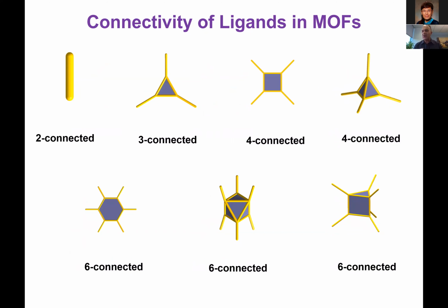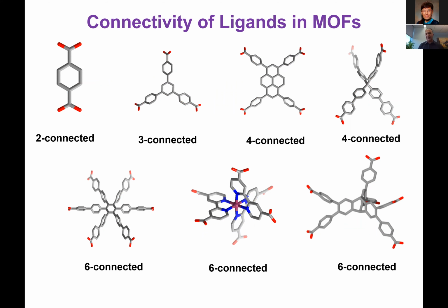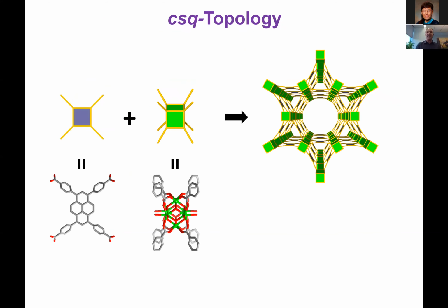With the organic ligands, we could play the same game. From 2 connected, that means you have, let's say, 2 carboxylic acids, 2 pyridines, 3 connected, 4 connected. The 4 connected can be a simple square or a tetrahedron, and the 6 connected can be an octahedron or benzene-like. So now we could start thinking about those geometric objects and convert them into chemical entities, as you see in these few ligands. If we want to build that CSQ topology, the triangles and the hexagons, you need those cubes and those squares.